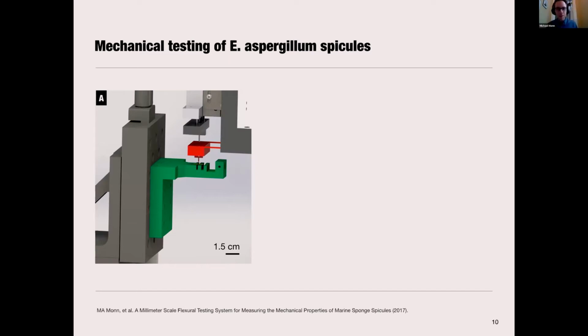And the first step in that process was constructing a mechanical testing device that could measure the flexural response of these spicules, and measure the energy dissipated during the propagation of a crack. To do that, we needed to measure forces in the range of micronewtons to millinewtons, and displacements in the range of microns to tens of microns. So we didn't find an Instron to be sufficient.